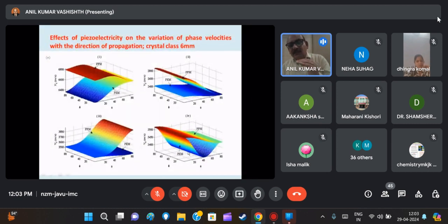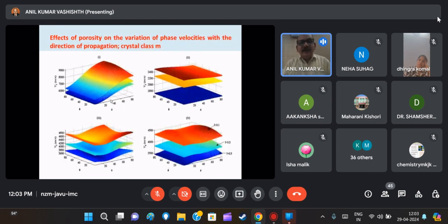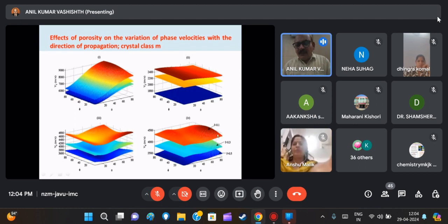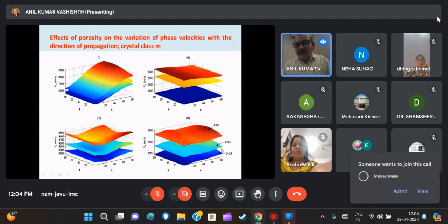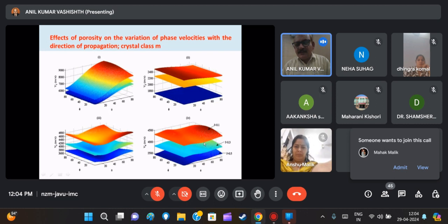as the degree of symmetry is as far as barium titanate and lead zirconate is concerned. Here, this difference in the model is affecting a considerable amount, and here is the effect due to the porosity. So, when the porosity is increased from 10 to 30%, notice a change.